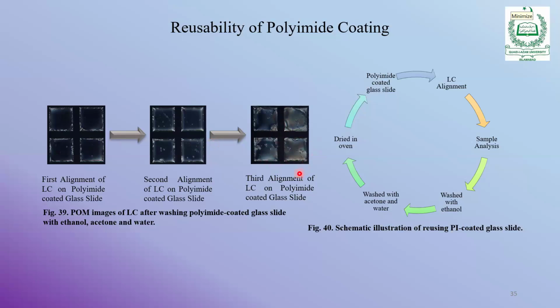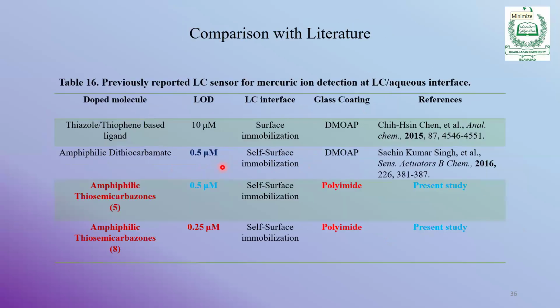And when we used it for the third time, we see that now it is showing some bright texture. It means the polyimide is not in the same condition as it was before. So already with this experiment, you can use this liquid crystal sensor twice. But we can optimize the conditions here and increase the reusability of the polyimide coating. Comparing with the literature,